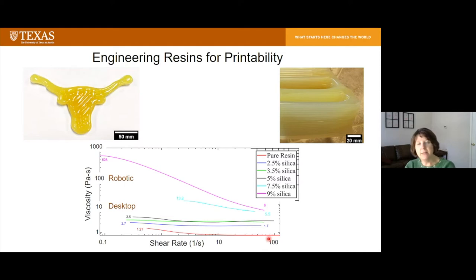So we add silica as a thickening agent. What we printed in the previous slide that I showed you is the green line here at 3.5% silica. But with our robotic system, we can go up quite a bit larger, to much larger fractions of silica or other additives like carbon fiber.